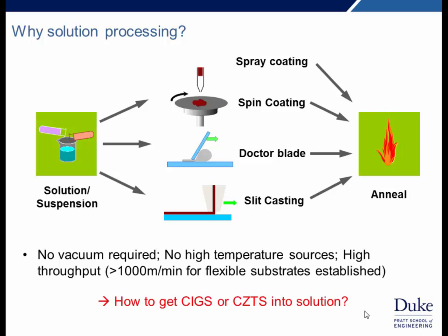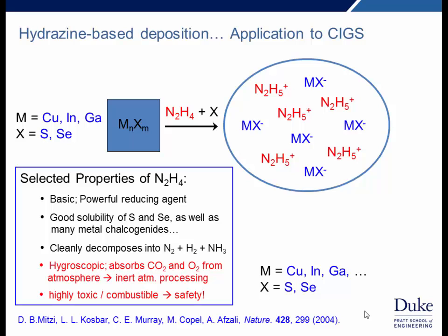The question is, how can we get these relatively insoluble materials into solution? And one approach we've looked at is using hydrazine, N2H4. This is a strong reducing agent, so it enables us to fully dissolve the chalcogenides in the solvent, and we can also incorporate extra sulfur and selenium, which is good for crystallization, and of course these elements are also needed in the final material. And the hydrazine decomposes cleanly, which means that the final films are clean from impurities. Of course, there are issues with toxicity and combustibility, and therefore the hydrazine needs to be used very carefully.